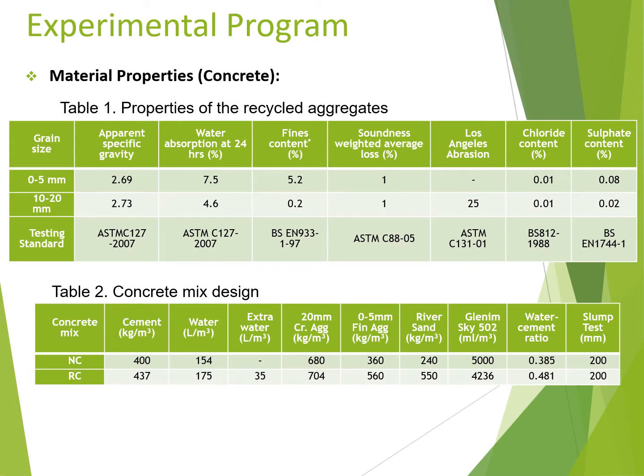Moving on to the material properties. First, the concrete. Two self-consolidating concrete mixes were prepared in this study in a ready-mix plant. One mix contained 100% natural aggregates and the other mix contained 100% recycled aggregates. Two sizes of coarse aggregates were used, which are 0 to 5 mm and 10 to 20 mm. The fine aggregates were natural sand from the river. The first table shows the physical and mechanical properties of the recycled aggregates used in the study. And we should also note that all the tested properties comply with the accepted values according to each standard tested.